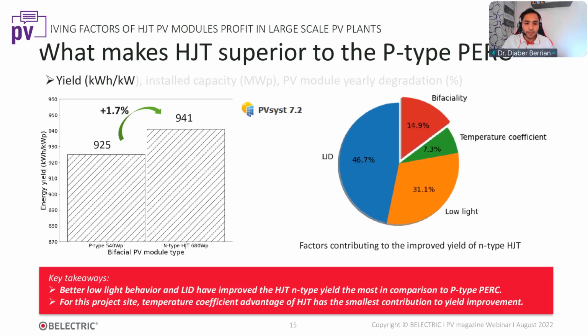So first, in terms of yield, we found that the heterojunction PV module for this project has higher yield, about 1.7% higher. And if we ask what makes this yield higher for heterojunction, you see here on the right-hand side the pie chart, which shows the different factors contributing to the improved yield for heterojunction. Mainly you see that the low light behavior and LID are the main contributors to higher yield. In second position comes the bifaciality, so the bifaciality factor of the heterojunction PV module are higher than the P-type PERC. And in third position, the temperature coefficient.